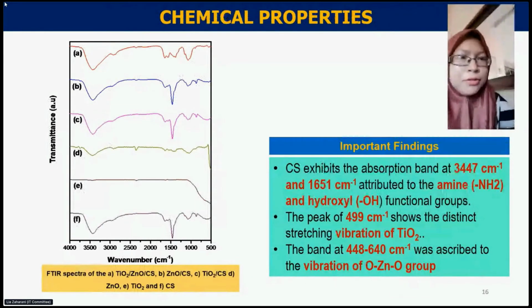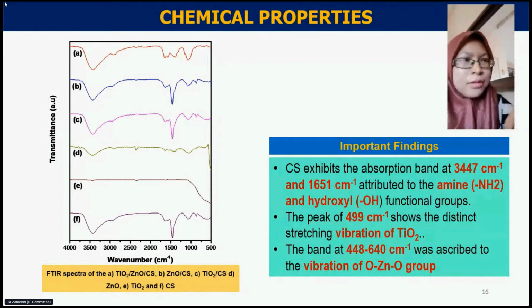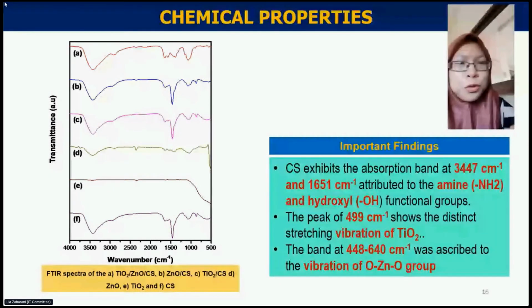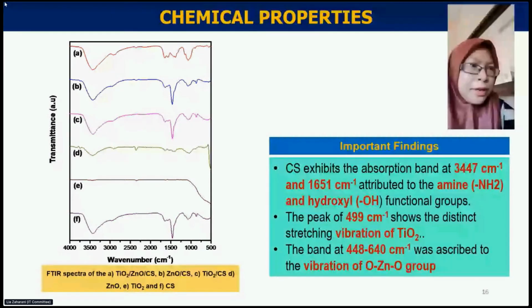Characterization using Fourier transform infrared (FTIR) spectroscopy analysis provides information regarding the active surface and the functional groups of these hybrid systems. The FTIR spectrum of the chitosan exhibits absorption bands at 3447 and 1651, which are attributed to the primary amine and hydroxyl functional groups. The FTIR spectrum of titanium oxide exhibits a broad absorption band at 3441, which confirms the OH stretching vibration of the adsorbed water on the TiO2 surface.